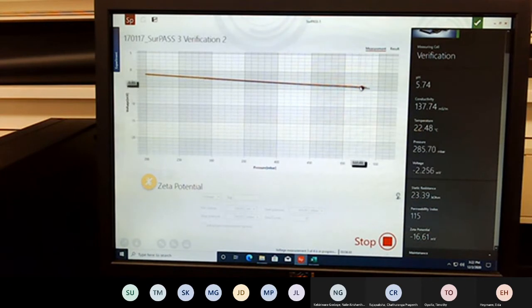All right, we can see a third, the blue curve forming over here, and it's falling again in line with all the previous ones. And they're all very close. Yeah, I mean, this is what you expect to see. Right. That means that with the sample, there are no gaps or anything in the way that it was prepared. And that means that nothing's really being washed from the surface as well.